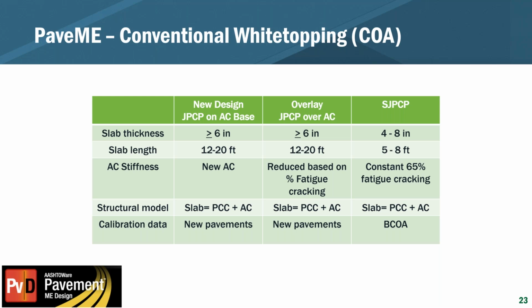And this is what we do in the BCOA ME as well, but with that, of course, you're relying on the bond, so you want the asphalt to be in relatively good condition. And so within those lower percents of fatigue cracking, it's not as sensitive as you'll see it is here for a conventional white topping. Now, when we use the new design and you design a concrete overlay over an AC base, how does that differ from the overlay design? It's pretty much exactly the same, with the exception that you're getting new asphalt, and the reduction of the stiffness of the asphalt base isn't accounted for because it's obviously a new base layer.